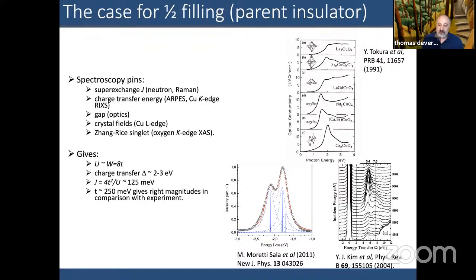The crystal fields have been measured with great accuracy using X-ray techniques. And also the so-called 6 eV peak is well understood from X-ray as well, as arising from a charge transfer excitation. And this gives us our nominal parameter set: U is on the order of the bandwidth, meaning that it is in an intermediate coupling regime, not much smaller or greater than the bandwidth. The charge transfer energy is somewhere around 2 to 3 electron volts. This gives a pretty decent value of J of 100 or so milli electron volts, giving a hopping of about a quarter or a third of a volt. So these are the parameter sets that I'm going to be working with, and I'm not going to be reporting what happens when you go outside of these limits in any strong direction.